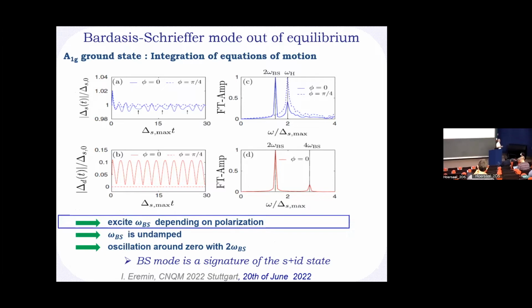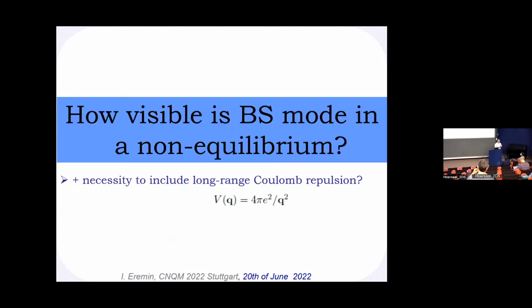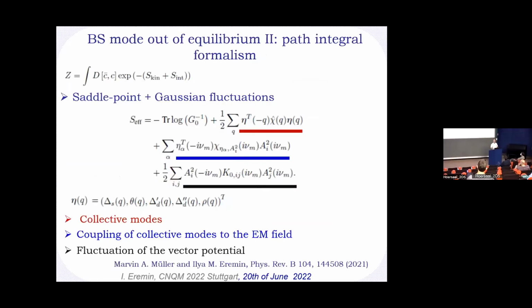And another thing is its form factor: it couples much more strongly to the electromagnetic field. Now, in order to proceed further, you also need to treat phase fluctuation correctly. So you need to take into account that your phase fluctuations become plasmons. So you need to take into account the long-range Coulomb repulsion, which you can also do. The only price you have to pay is that you cannot do it in the Anderson pseudospin formalism.